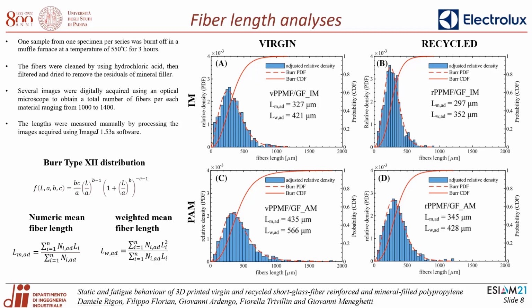Starting from the same process to produce the pellets of both virgin and recycled compounds, one can hypothesize that the higher fiber breakage can occur due to different rheological properties between virgin and recycled matrix, but further investigations on these are ongoing. Looking at the same material, for both materials the mean values of the fiber length are higher in specimens produced by PAM than by IM. This could be due to the higher shear rates that occur in the injection molding process that are known to be the main cause of fiber breakage.